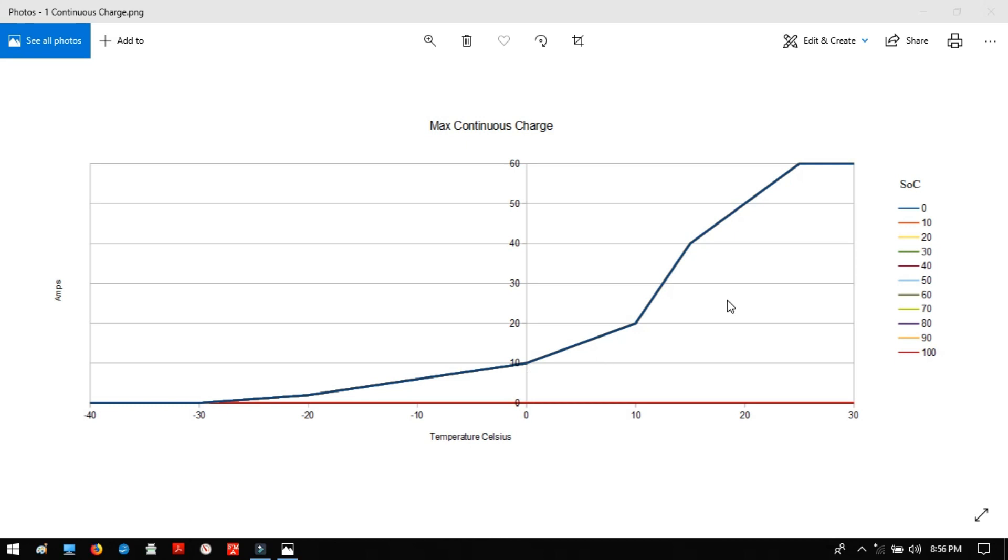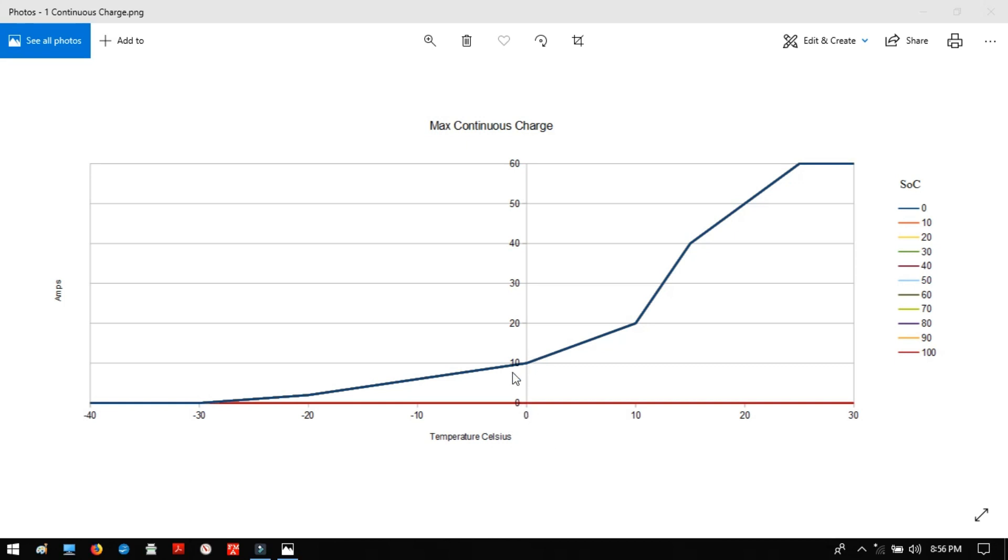This is the continuous charging graph. And you can see that how hard I can be charging it continuously actually starts - I should be reducing it as low as anything below 25 degrees Celsius. I should be starting to slow down how much I'm continuously charging it. So for practical purposes, we can say this 60 amps up here at 25 degrees Celsius continuous charge is roughly as much wear and tear on that battery as 10 amps of charging down here at zero degrees Celsius. But I can actually go below that. You can go all the way down. I can go down to say minus 15 and still be doing say five amps of charging.